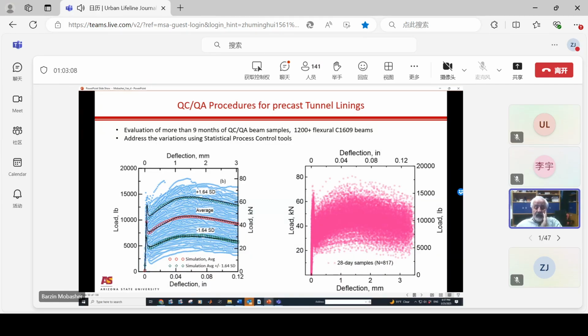So here's a problem. People would say that, oh, you have to calculate characteristic value of these, and then you look at the standard deviation and reduce the data by standard deviation. And my answer is no. This is because the fiber distribution is random. We don't need to really worry about how the results are coming, because what we need to do is to look at the fact that the first crack strength, first of all, if you plot the first crack strength as a function of residual strength, it means nothing.